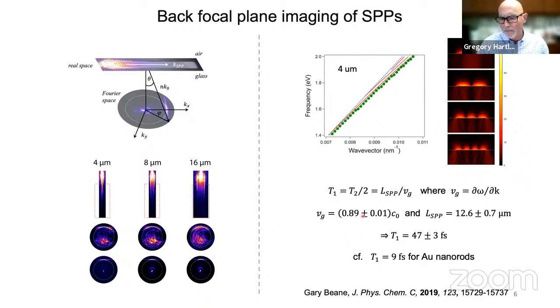So in any event, we do this measurement. We get a group velocity that's almost 90% of the speed of light, right? So these things move very, very fast down the wire. The propagation length is about 12 microns. And so when we take these two measurements, we work out a lifetime of about 47 femtoseconds, right? So actually still really, really fast, okay? But almost 5 times longer than what you get for the gold nanorods.